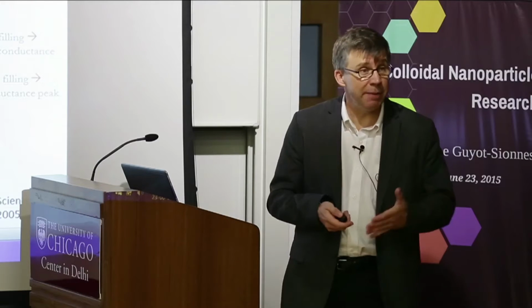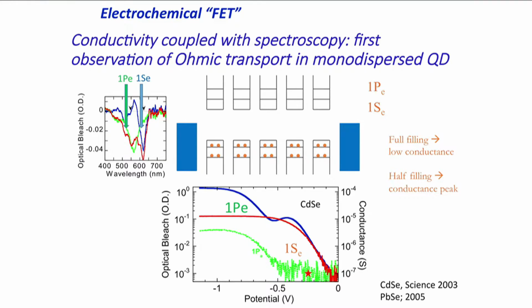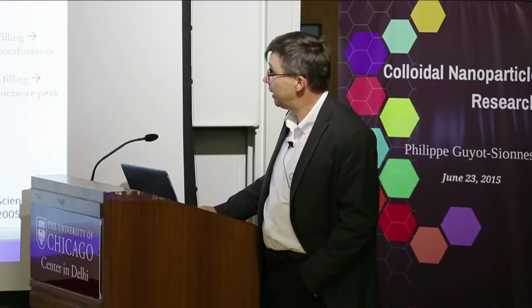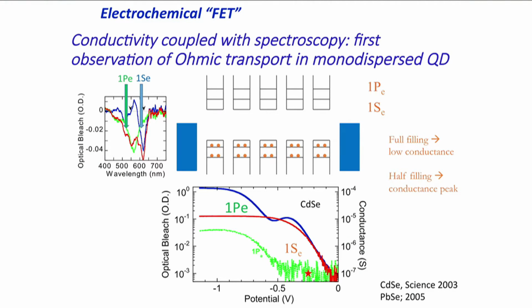And so indeed, the same kind of films were then measured for conductivity by putting them onto an interdigitated electrode and applying a small bias across. And what we saw was this very nice demonstration of conductivity. I have a little animation here. These are the Fermi levels of the electrodes. When we apply a bias, we raise them to the point that electrons start being able to hop onto the nanoparticles all the way through. This is what happens on this part here. And at the same time, we could monitor the spectroscopy and see that those states are indeed being occupied.